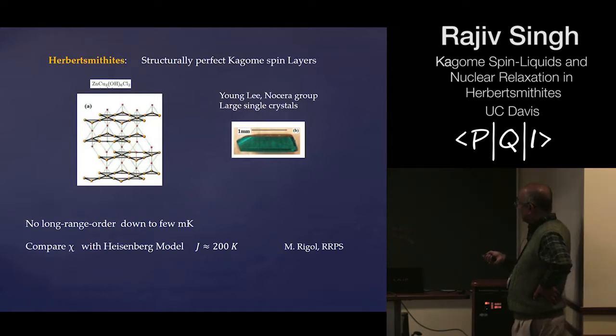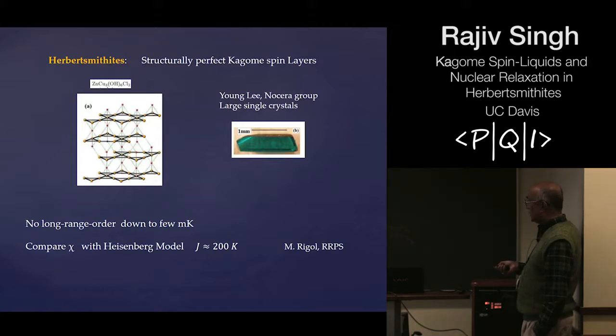People have been able to make very large single crystals, which are needed for neutron scattering experiments. And this material, one can easily show just by comparing, for example, the susceptibility that it has, if you think in terms of the Heisenberg model, an exchange energy scale of order 200 Kelvin, but down to a few millikelvins that people have gone to, the system shows no sign of long range order.